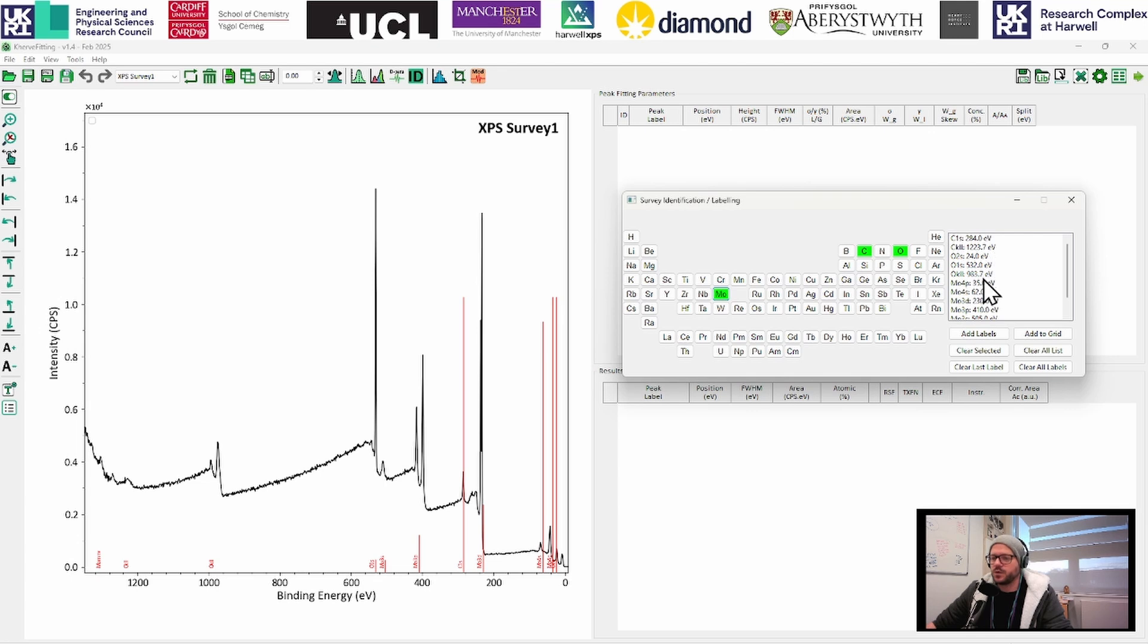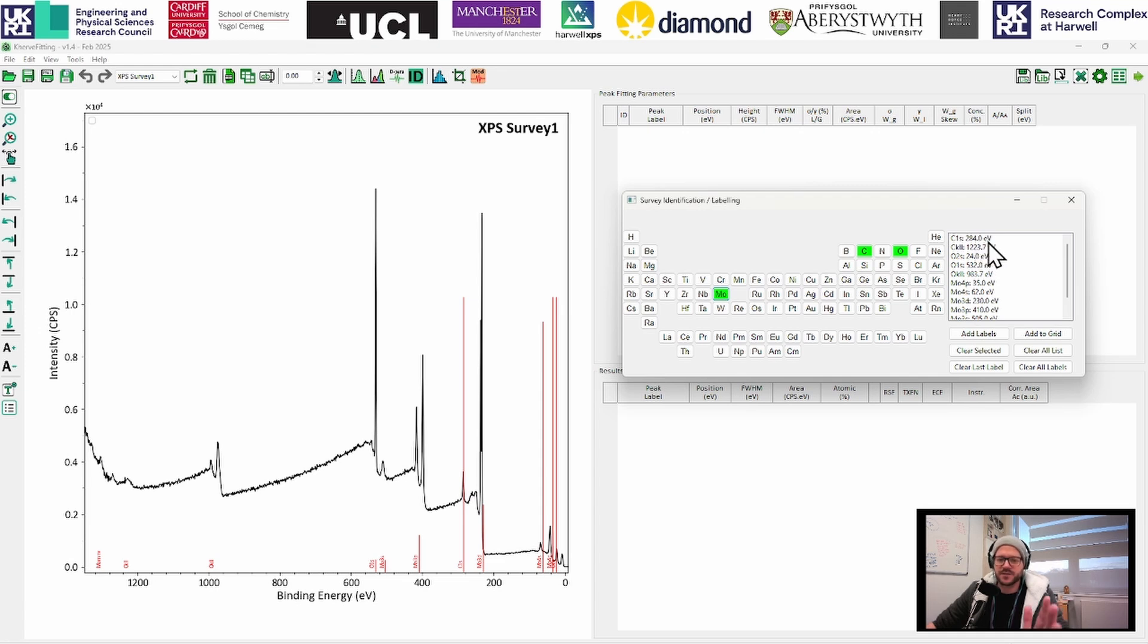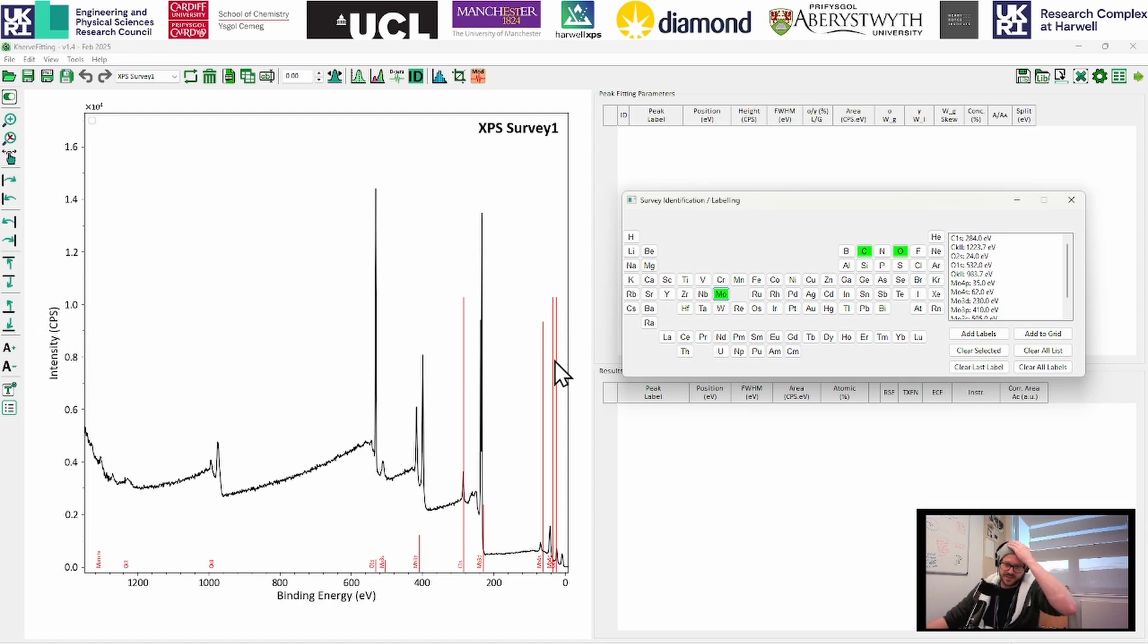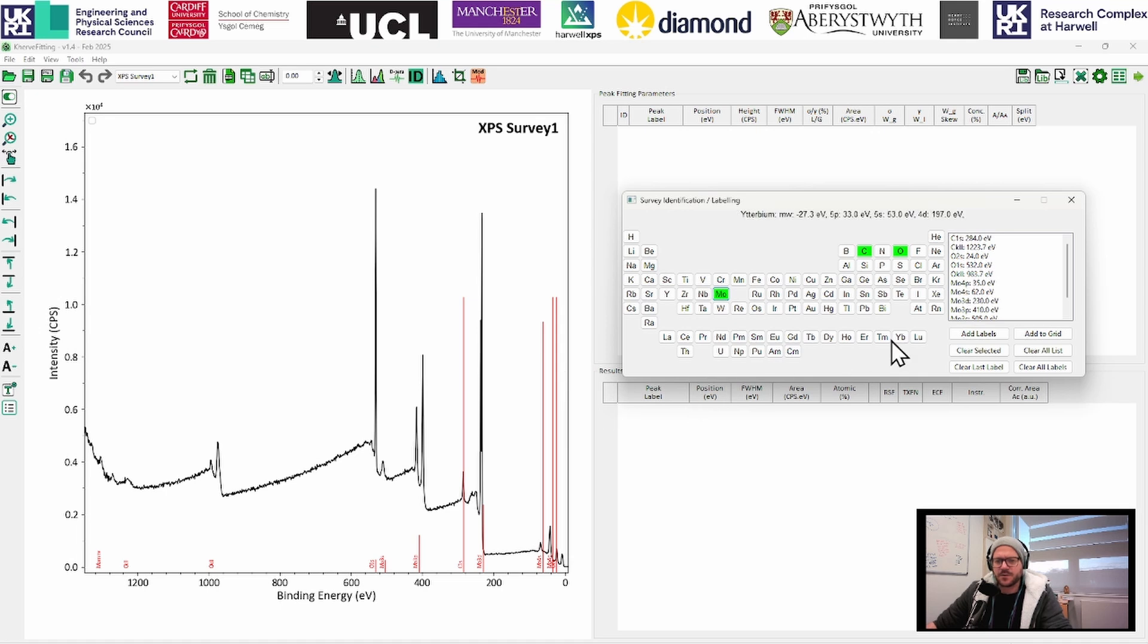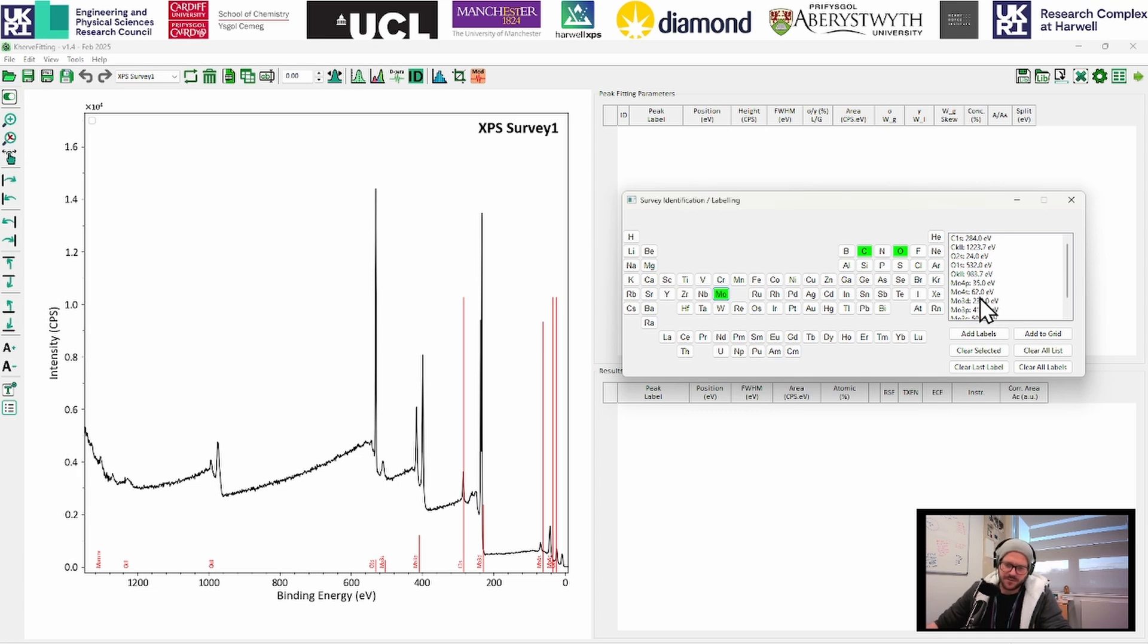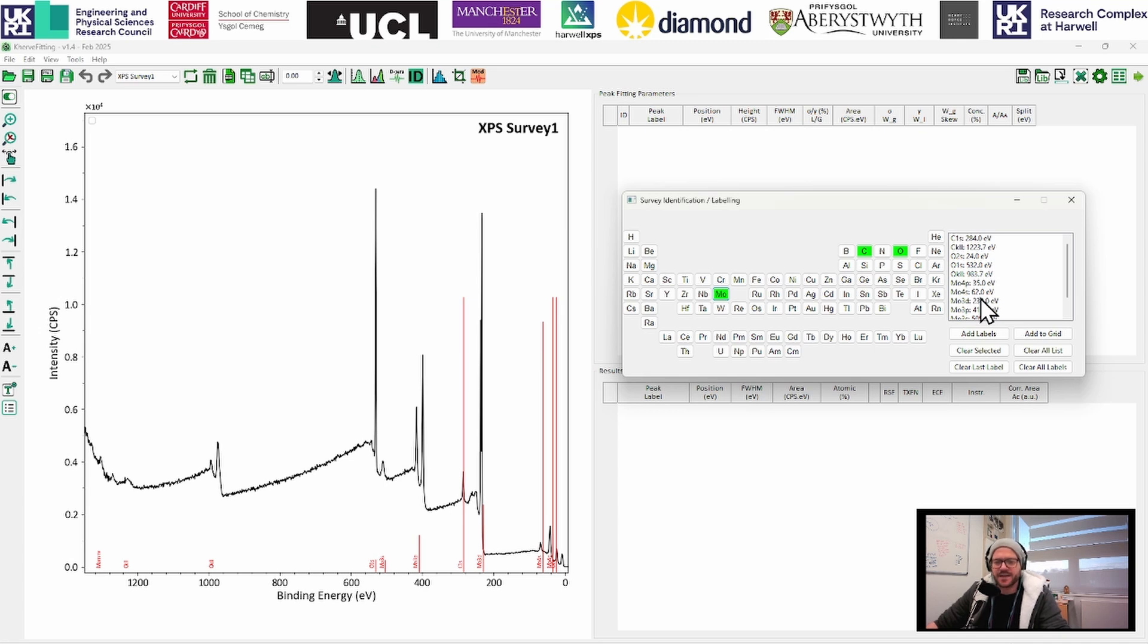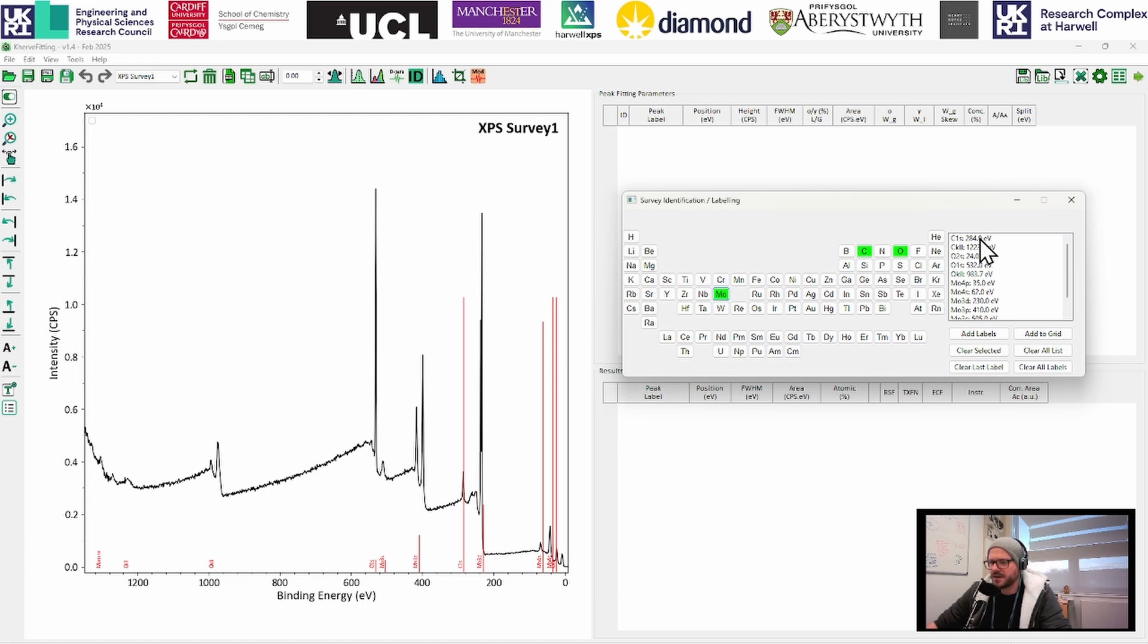And what you can see on this little side panel here is we now have a bunch of possibilities for all the different transitions. You can also see the peaks with the red lines, they label with the different peaks that you might see and the expected kind of intensity ratios. So we can kind of line those up with the peaks that we have as well. So we can see, yes, we've got some molybdenum 3D, some molybdenum 3P, the 3S, the O1S, the C1S. So yeah, we've pretty much got what we expected.